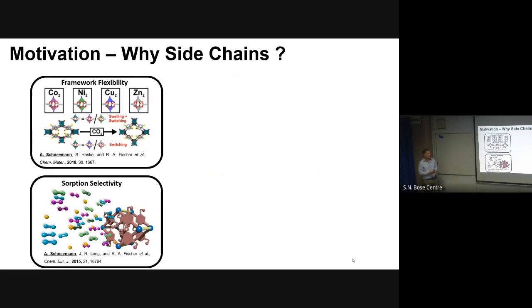The first question is probably why do we want to use sidechains? During my PhD, I already worked quite extensively with sidechain modified metal organic frameworks, and as a researcher, you often take something that you already know and combine it with something new. We found that in certain types of metal organic frameworks, sidechains make it flexible, so they can change their pore environment upon adsorption, for example. And these side chains also induce some adsorption selectivity for certain gas molecules.